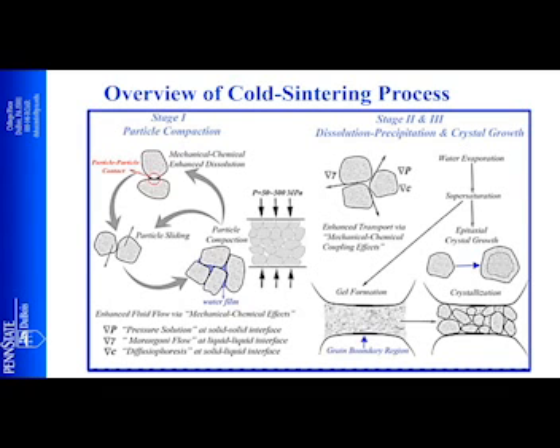So when you apply pressure and time, you end up having some sort of liquid phase between the particles. And there are several opportunities in which this liquid phase can be used. You can use it as a transient liquid phase in the case of sintering, to give you much better strengths. Or in the case of green parts, you can get better green strengths, which allows you even to do machining. Not only that, you can also use that to create some coating. And that allows you to think about soft magnetic composites. So there are several opportunities for this project.